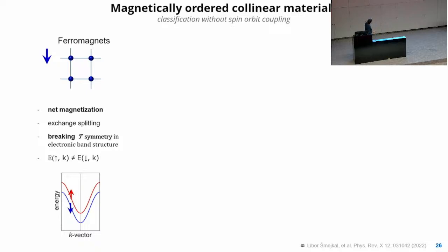Of course, simplified, we have here this momentum vector, and here the energy, and typically we would have two bands split sort of isotropically in all the space between the spin up and spin down. And that's also why these materials are so favorable for spintronics applications, and all of the current applications are based on those, because we see these blue and red lines. So clearly when we now send a current, for example, with an energy here, it has to be on the red state, so it has to be spin polarized.